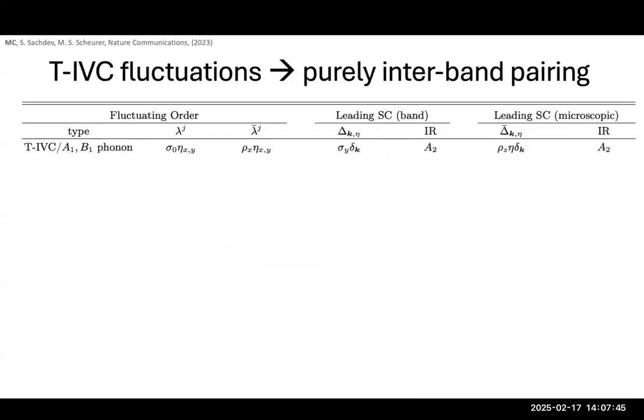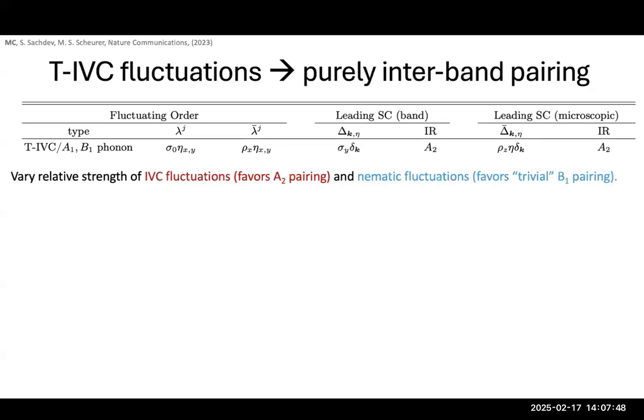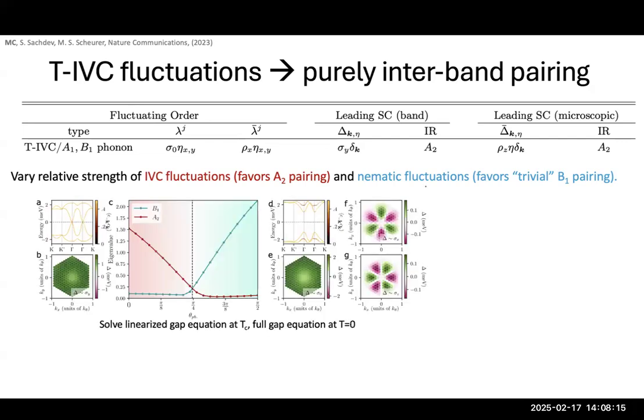And now we want to zoom in and study this within a microscopic model. So to do this, we study a continuum model description of TBG, where we'll be solving the linearized gap equation at Tc and the full gap equation at zero temperature. And we add the interactions you get from IVC fluctuations, and then we tune the relative strength of these interactions with the interactions you get from nematic fluctuations to see the competition between different states. And what we find from the linearized gap equation, so here I'm plotting the eigenvalue we extract from that, is that the leading state indeed is this A2 state in this regime.